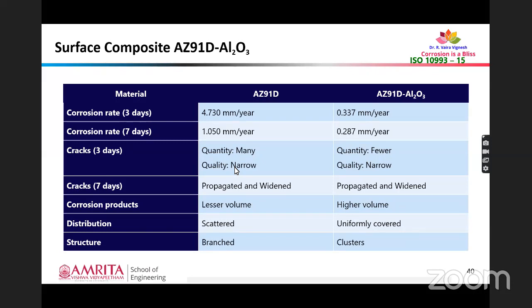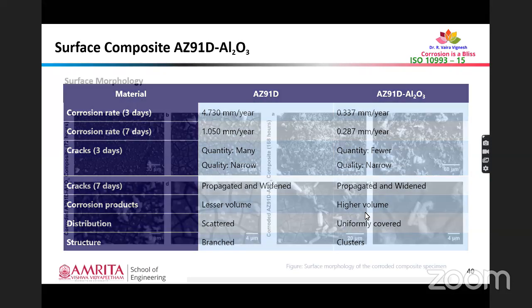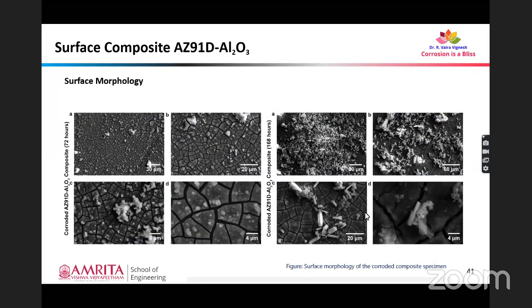And coming towards the distribution of corrosion products, in AZ91D, the corrosion product distribution was highly random and scattered. But in the case of the composite, the corrosion product was uniform. It means there is a complete layer of formation of corrosion products. And the structure was branched in the base material and clustered in the AZ91D aluminum composite. So here we could see how the corrosion products are distributed and how the crack has propagated over a period of 3 days and 7 days in the base material and the composite.